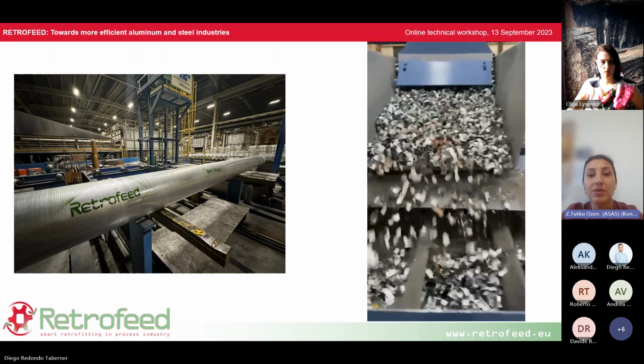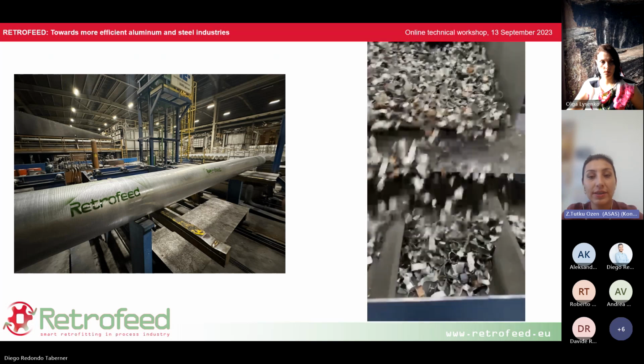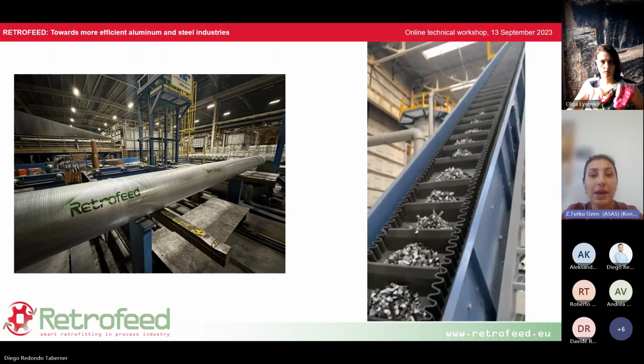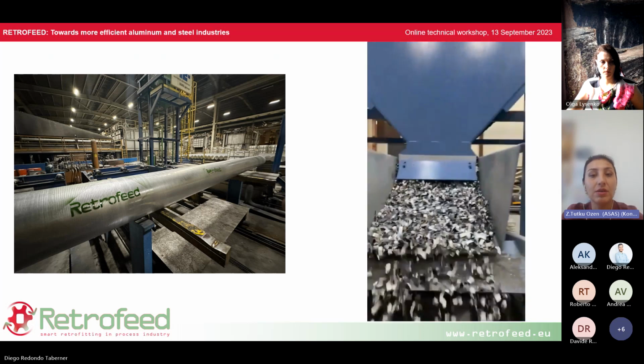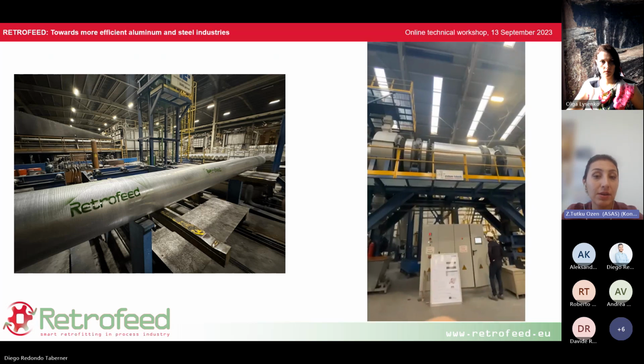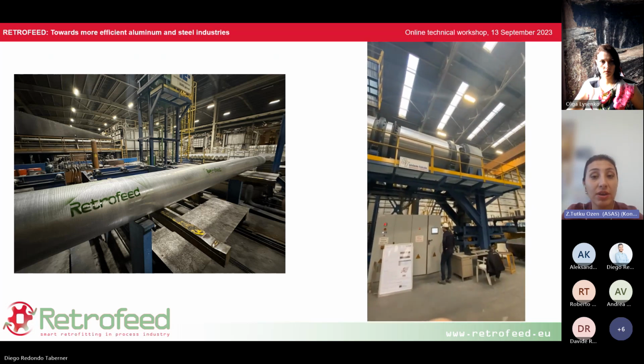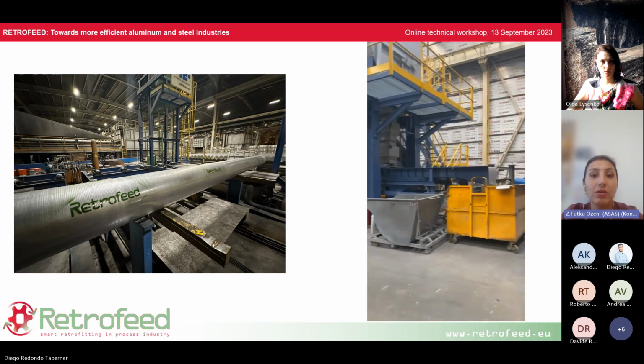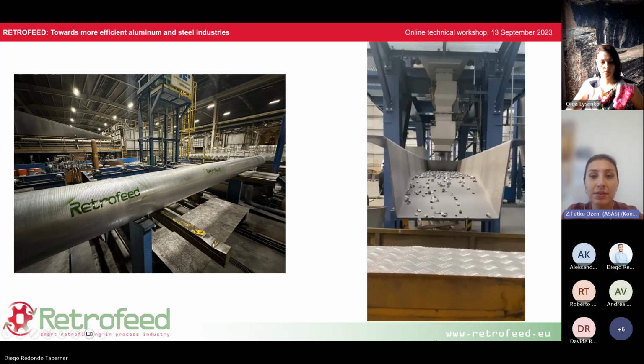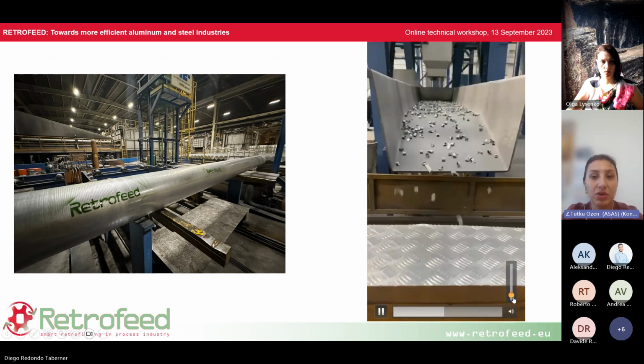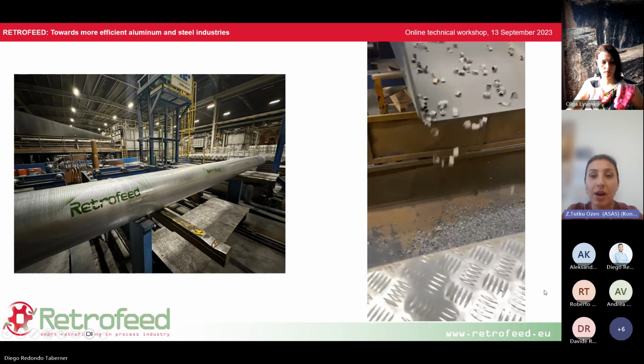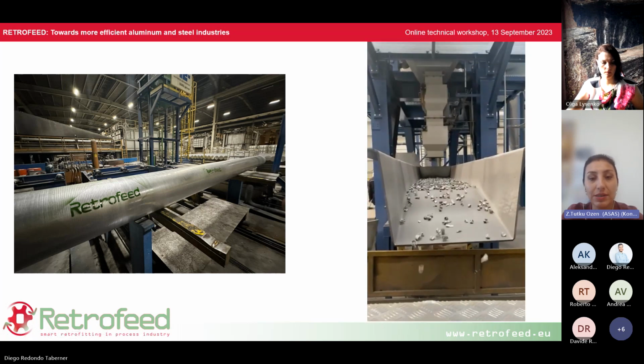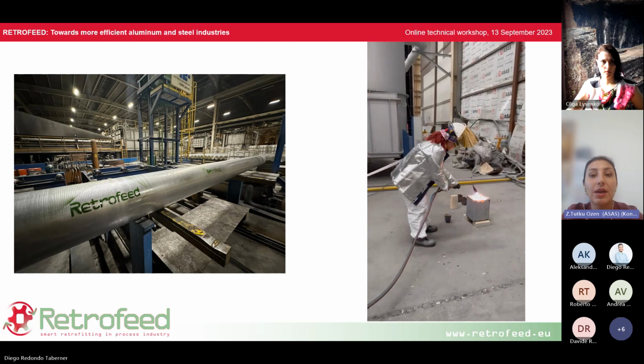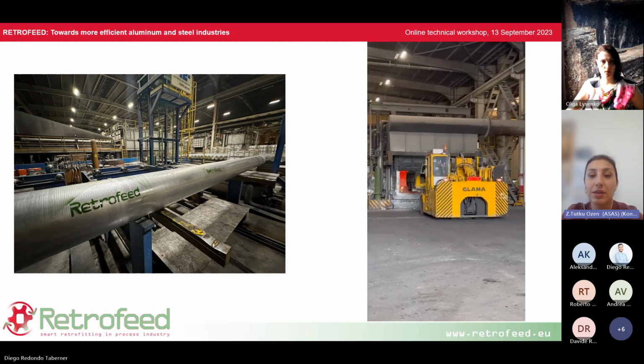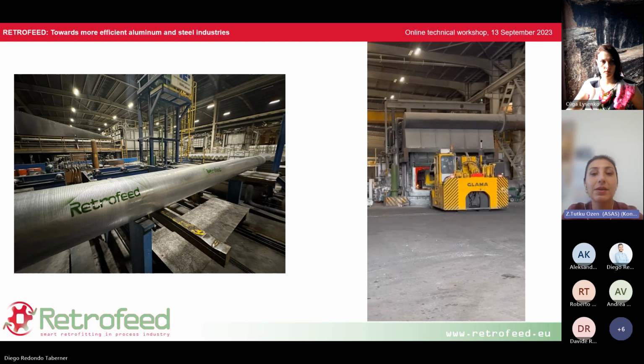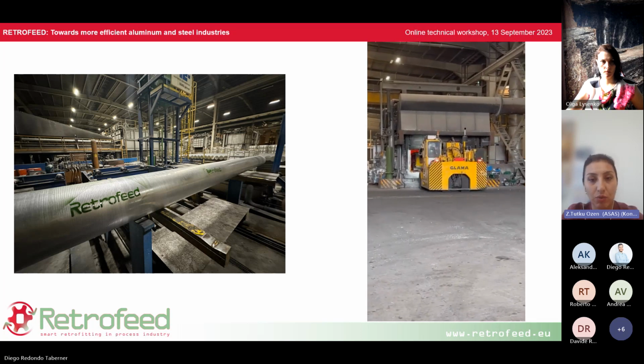As you see in the delacquering system, first of all, shredded, painted and lacquered scraps enter from the bunker to the system, and they are transferred to the delacquering rotary kiln from the conveyor. The rotary kiln rotates with a constant speed and constant temperature in order to carry out the delacquering process, which is decoating of these scraps. The decoated scraps were tried at lab scale first, and then in industrial scale production.